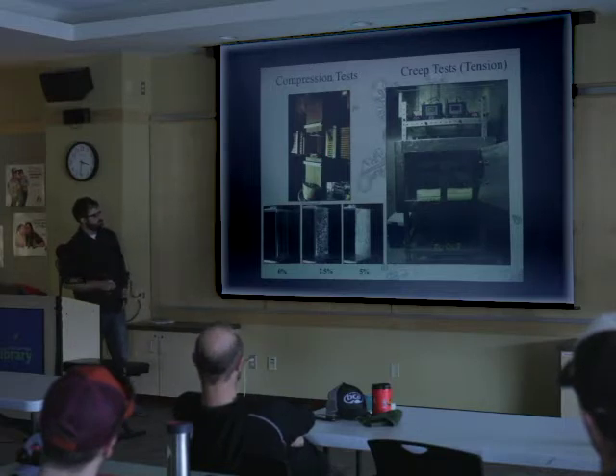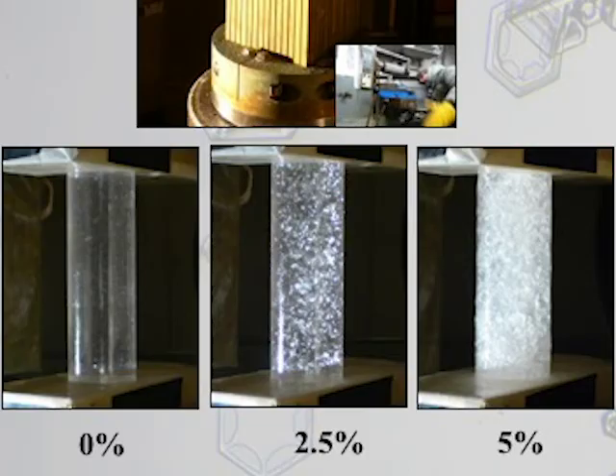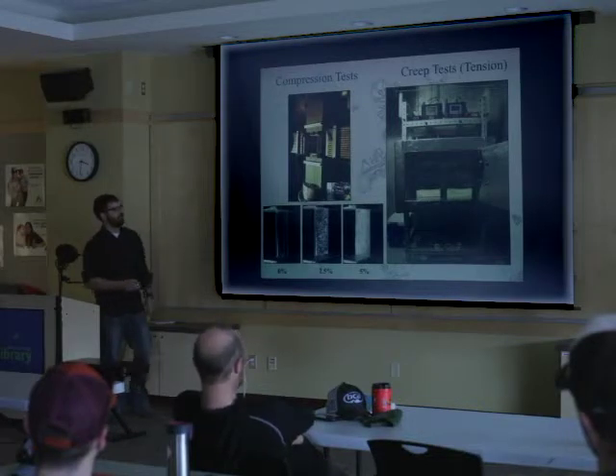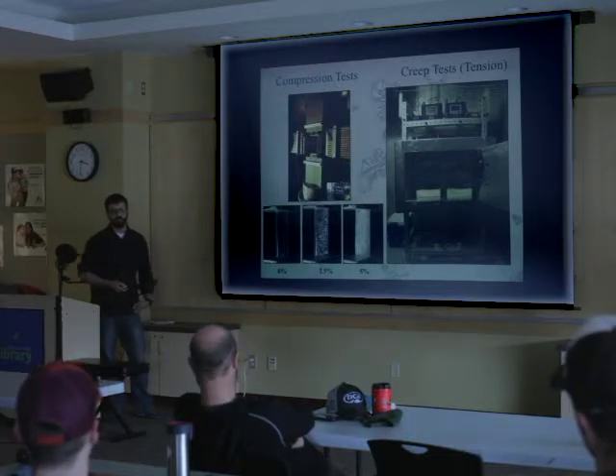So this is what one of these cylindrical ice specimens looked like when you compressed it to 5% strain. This was a really fast compression test, over less than an hour. And you see that you got lots of cracks happening until it was pretty much cracked all the way through, but you could still take this thing out and hold it. It still had its structural integrity, which is pretty impressive when you think about it was compressed 5% in less than an hour.